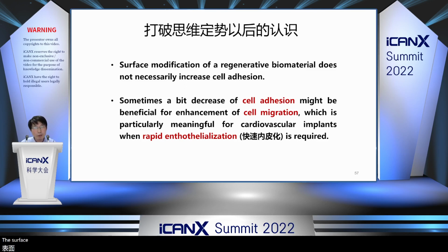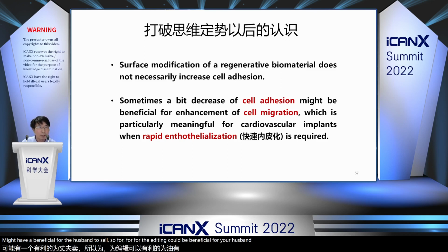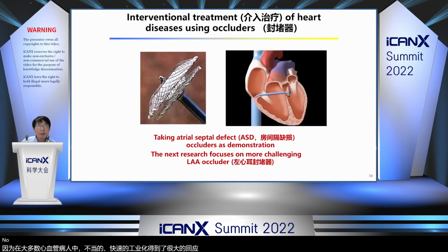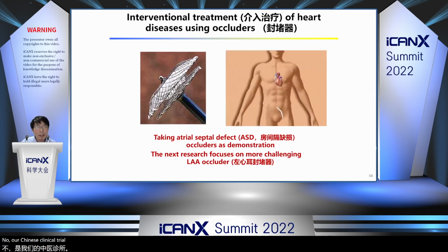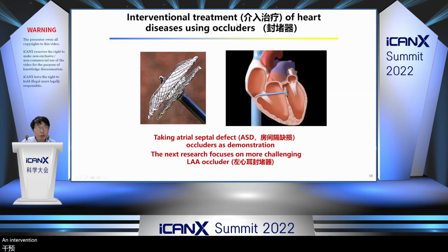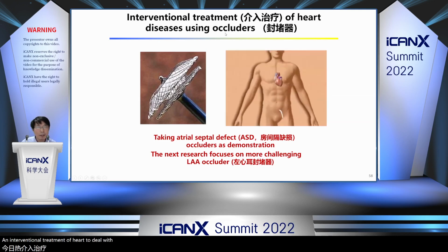The surface modification of a regenerative biomaterial does not necessarily increase cell adhesion. And sometimes a bit of decrease of cell adhesion might be beneficial for enhancement of cell migration. It is particularly meaningful for cardiovascular implants because in most cases for cardiovascular implants, rapid endothelialization is much required. Now, our clinical translation is about interventional treatment of heart disease using an occluder.